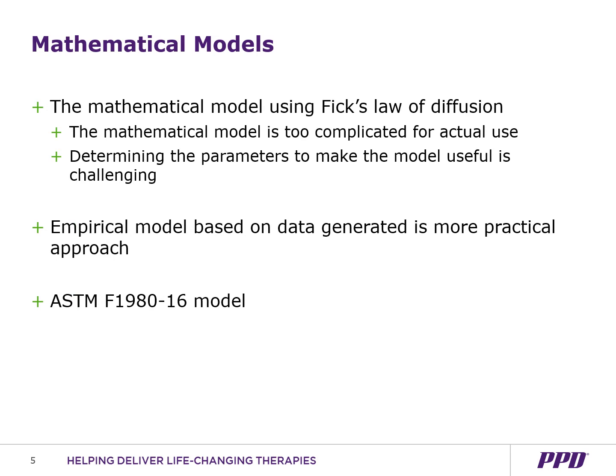And that makes modeling this mathematically quite challenging. There is a mathematical model using Fick's law of diffusion. However, its practical use is limited, and it's a very complicated model with a lot of different parameters. So determining those parameters to make the model useful is quite challenging. So developing empirical models based on data generated is a more practical approach. One of these studies uses models focusing on accelerated aging, which is the ASTM, or the American Society for Testing and Material, F1980 model. So I'll start by explaining this model in a little more detail.